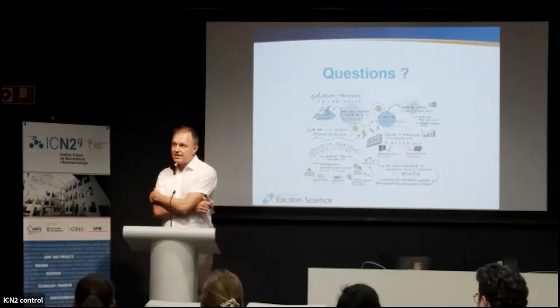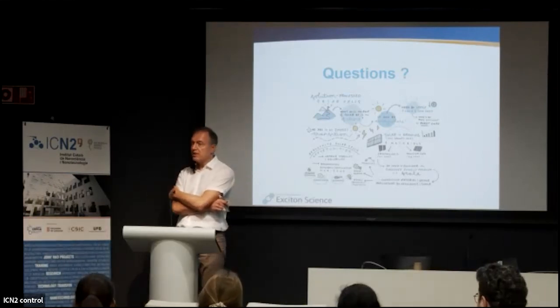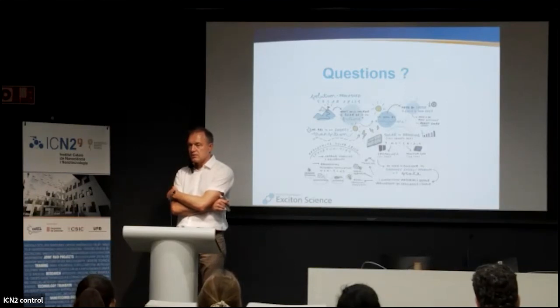Those of us that work on the use of additives for this halide perovskite in solution processing are trying to do the following. If we see this ion movement, we are trying to trap the ions and stop this movement, immobilizing them with additives. But what you saw in your crystals is that, of course, you have movement inside, and you are not going to be able to put additives inside the crystal to make it immobile. That's a problem. Yes, I think, in general, the halide mobility is a problem.